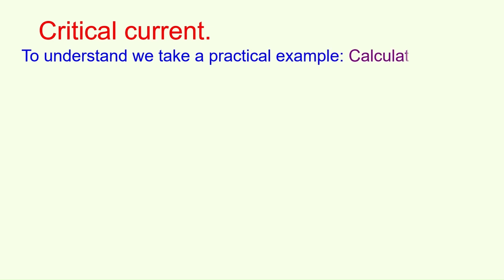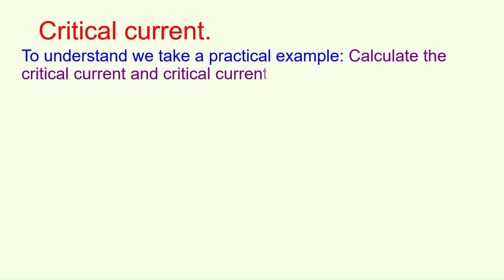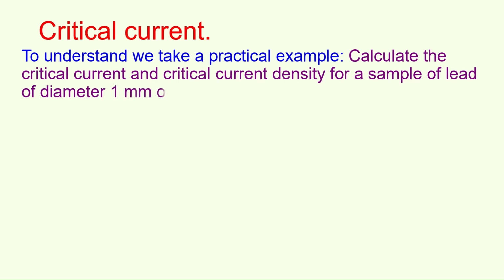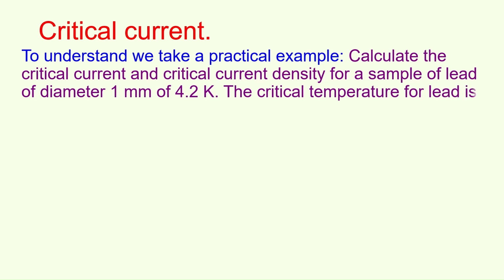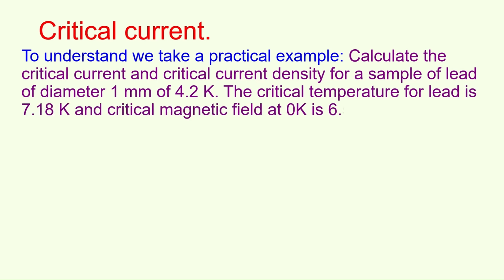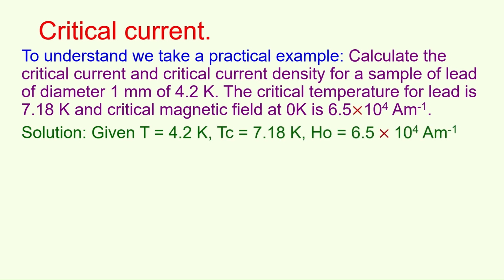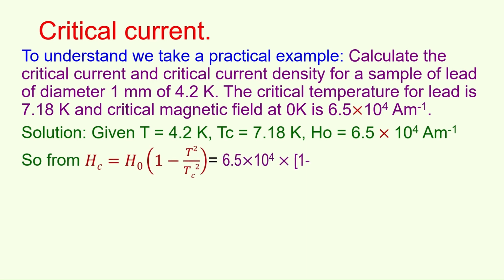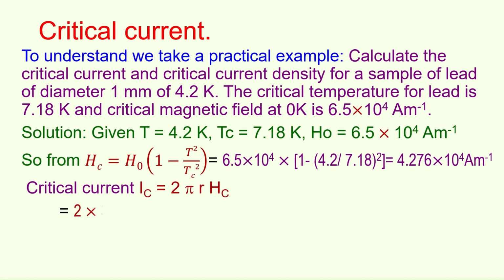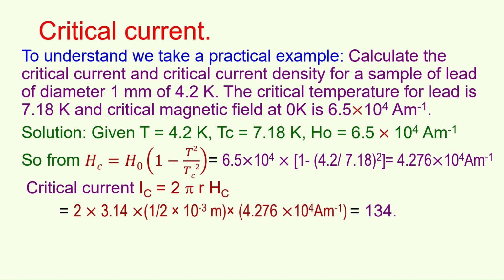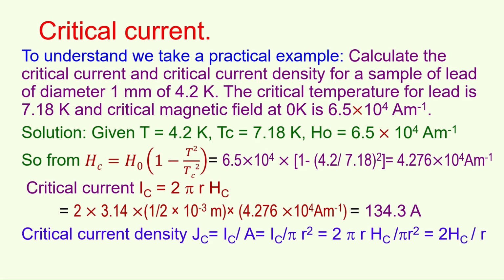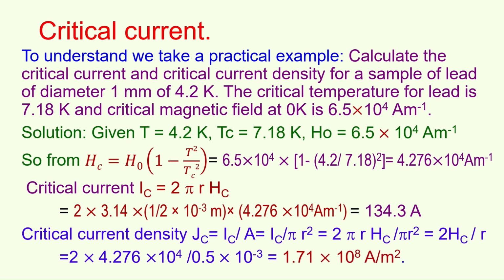To understand, we take a practical example. Calculate the critical current and critical current density for a sample of lead of diameter 1 mm at 4.2 Kelvin. The critical temperature for lead is 7.18 K, and the critical magnetic field at 0 K is 6.5 times 10 to the power of 4 amp per meter. Solution. Given T equals 4.2 K, Tc equals 7.18 K, H0 is equal to 6.5 times 10 to the power of 4 amp per meter. From the formula Hc equals H0 times (1 minus T square divided by Tc square), and critical current Ic equals 2 pi r Hc equals 134.3 A. Critical current density Jc equals Ic divided by A equals Ic divided by pi r square, which is equal to 1.71 times 10 to the power of 8 amp per meter square.